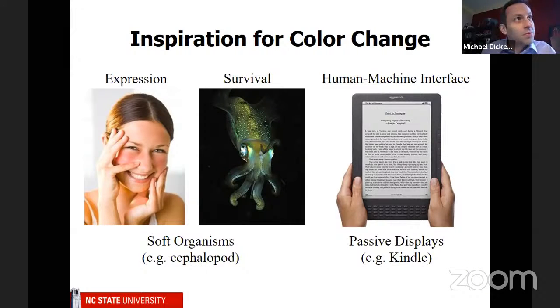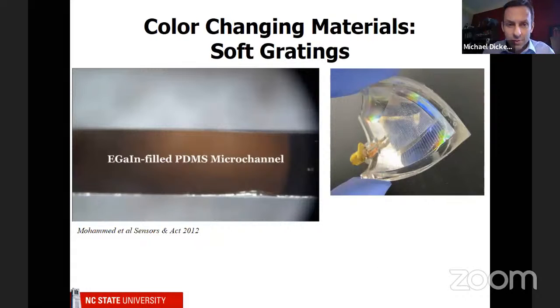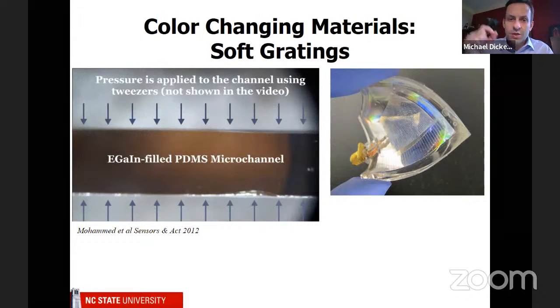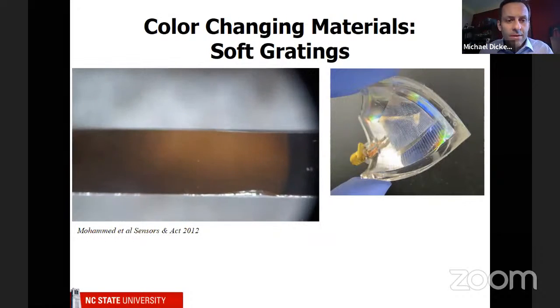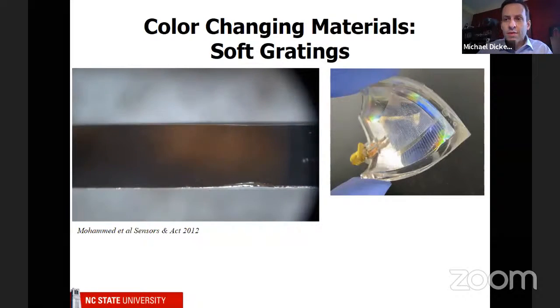So I'm going to show you 2 examples, I think. The first one is very simple. This was a device that we made a long time ago. And one thing that was very weird was that you see there's some color. For some reason the liquid metal is colorful. And so this caused us to do a kind of curiosity-driven research where we took the liquid metal. Remember, this is eutectic gallium and indium, and we put it into a microchannel, a very small channel, and then we squeezed it. When you squeeze it, just using a little bit of pressure, we found that we could see some color. And that was very, very weird.